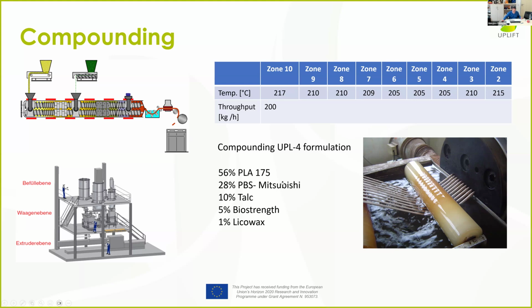For this compound, we use the temperature profile of PLA because it was the main component of the compound, and of all the components, it has the highest melting point. So the mixing was very, very good. And you see here the different zones and the throughput of the extruder, which was 200 kilograms per hour, which is our smallest extruder. Normally we have extruders with 500 and 1,000 kilograms per hour, but this was our smallest one. And here you see exactly this situation where the strand comes out from the die, and it's getting cut and granulated.